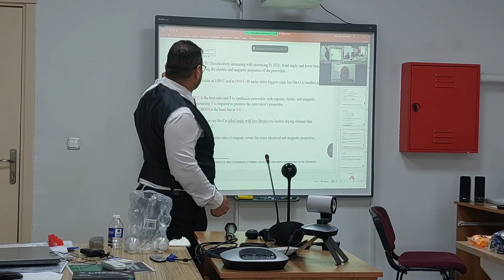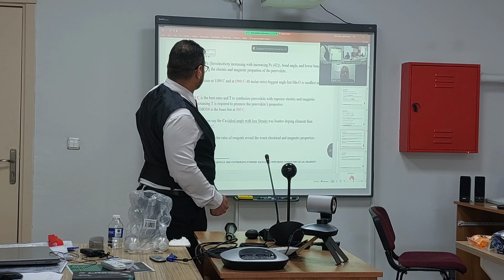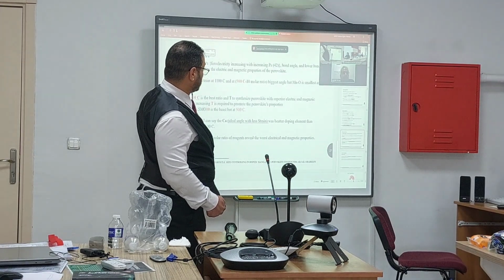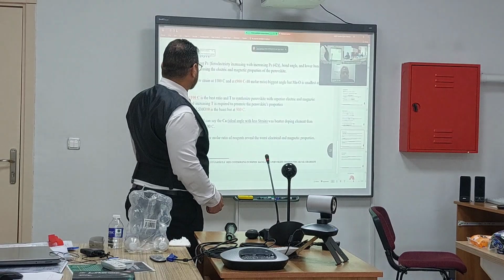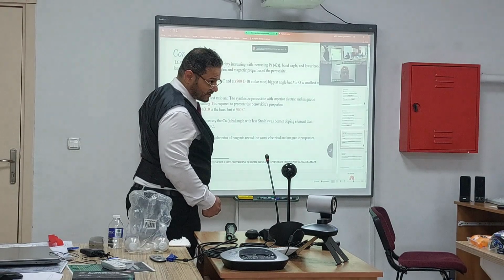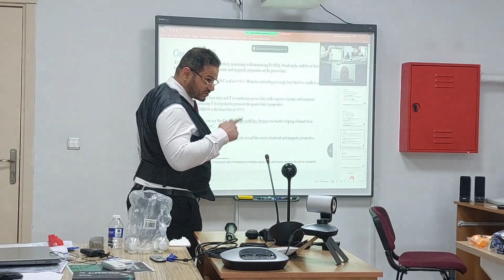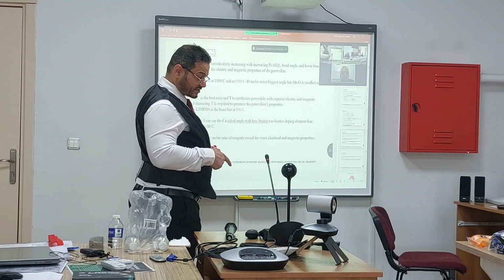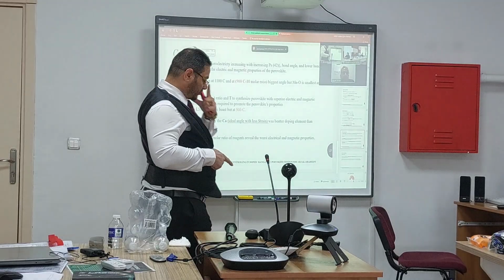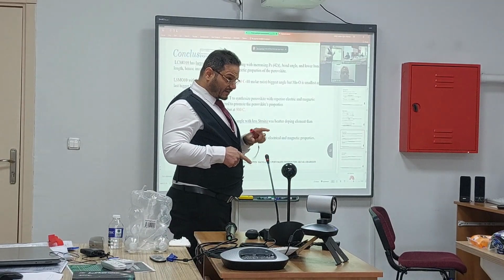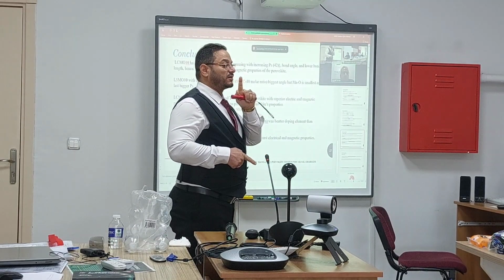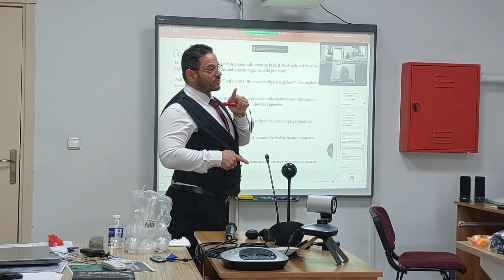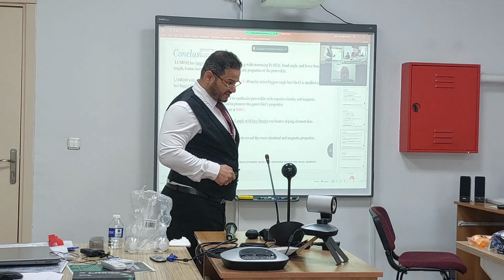At strontium 10 molar ratio, low strain. At 900, 10 molar ratio, the biggest angle, but the smallest particle size. And don't forget, I noted an important thing in the plots: the particle size was almost always bigger at 1 molar ratio at the same temperature, but when you increase the temperature, approximately all of these increase. That's it.